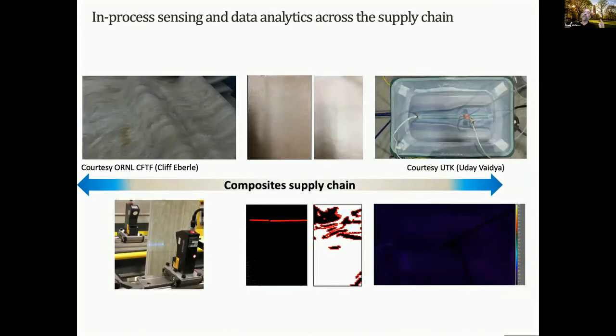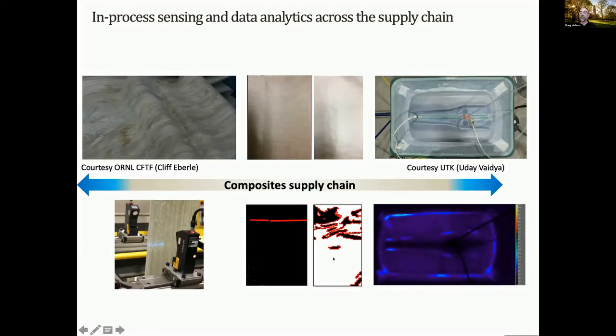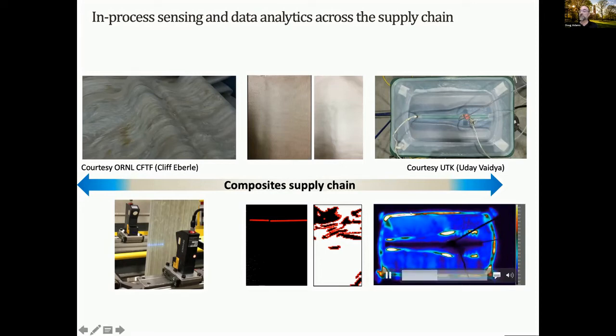So, if you think about this technology that I'm talking about, where we're actually using temperature changes on the surface to infer what's happening beneath the surface in the process to try to identify flaws, this is a technology that you can actually apply in a lot of different modalities. So it's not just temperature measurements like I'm showing over here in this part that was manufactured by University of Tennessee, Knoxville, Uday Vaidya there, where we're seeing pockets of resin-rich material that eventually lead to embrittlement in those areas of the material. So we're able to see those flaws form during the process.